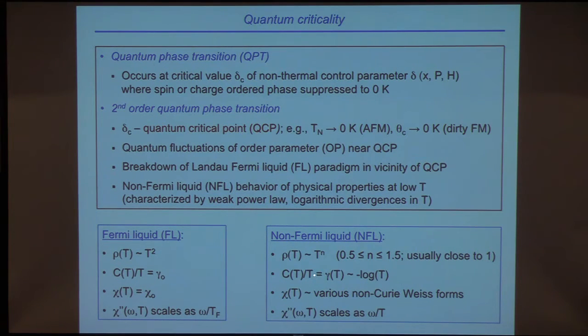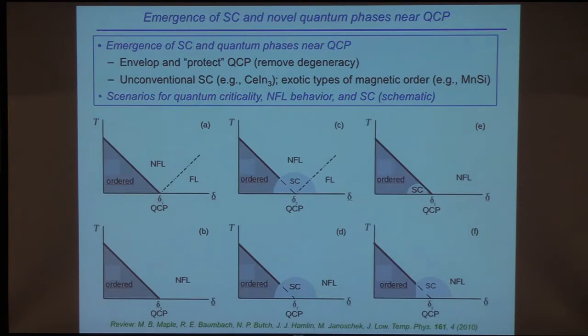The specific heat over temperature usually diverges as log T, or a weak power law that's close to that. You get various non-Curie-Weiss forms of susceptibility, and then in some cases you can get this omega over T scaling, where the Fermi temperature just gets lower and lower and gets renormalized through these quantum fluctuations. Okay, and so I've schematically indicated here some scenarios.